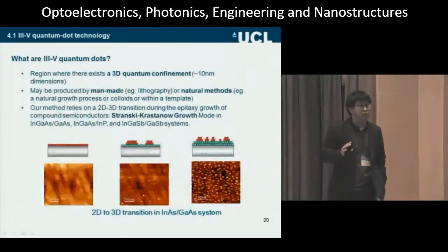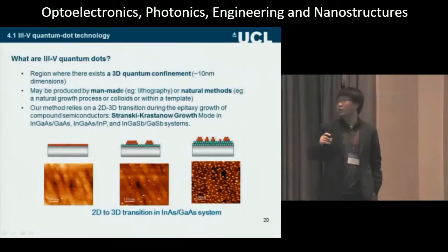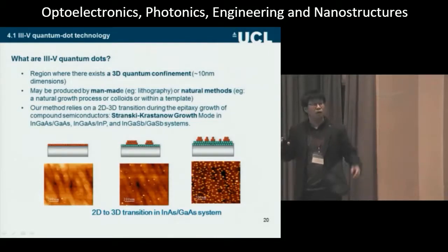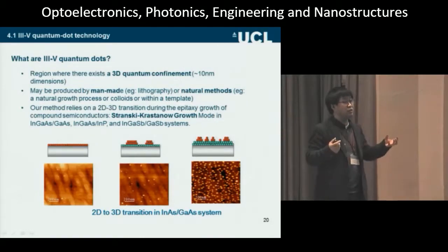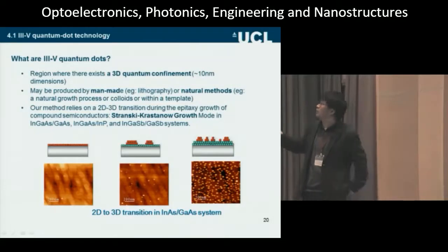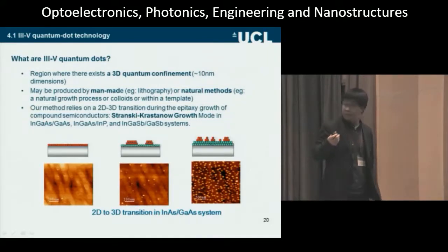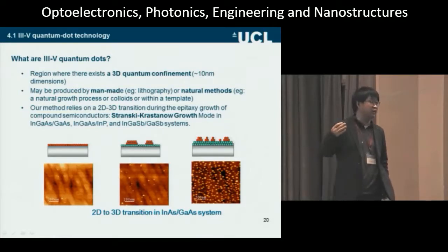How do you make III-V quantum dots? After the quantum well laser was successful and demonstrated in a lot of products, quantum dots were on the table for a long time. The first approach is man-made, using an etching method. With this method, you get low density, but you also have to introduce a lot of defects with the man-made process. Then, about 30 to 40 years ago, the SK mode was used for quantum dot growth. We can make very high density and low defect, or defect-free, quantum dots.